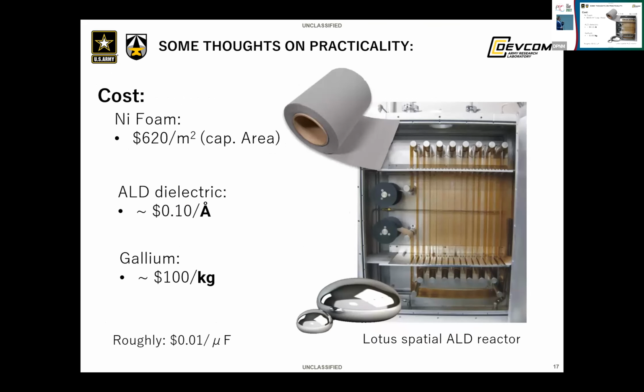Now, I don't want this work to just be a total fantasy. So I got some back of the envelope calculations of what this could cost. Commercial nickel foam comes in rolls. Here's the area. ALD dielectric, maybe someone can give me a better number than this. My local ALD guy told me that this is about what you could expect. And then gallium is about $100 per kilogram. So given the commercial area of the foams, if you don't do anything fancy to crush them partially or anything, you're on the order, I know I'm probably off by at least 2 orders of magnitude, but you're on the order of cents per microfarad. So if you want to talk about a regular capacitor, you can't be on the order of $10 or $100 per microfarad, or you just should stop what you're doing.